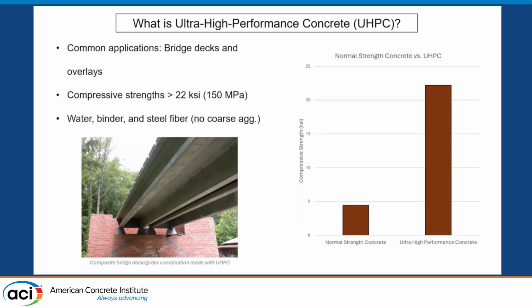And the cool thing about UHPC is that the compressive strength is around 22 KSI, whereas normal strength concrete is between 2 to 4 KSI. And the composition of UHPC is water, binder, and steel fiber, with no coarse aggregate, hence the low porosity.